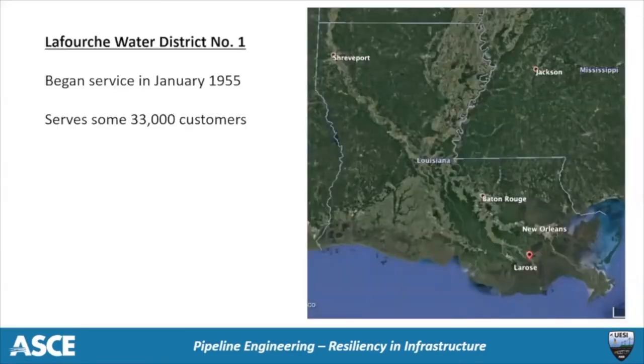Lafourche Parish is located some 45 minutes to an hour southwest of New Orleans in the southern Louisiana Bayou country. The area has very aggressive soils, which is the reason in 1958 that the Water District was interested in working with the iron pipe industry to investigate this idea of corrosion control using polyethylene film as an encasement to protect the pipe from the aggressive environment that is not uncommon in this region.